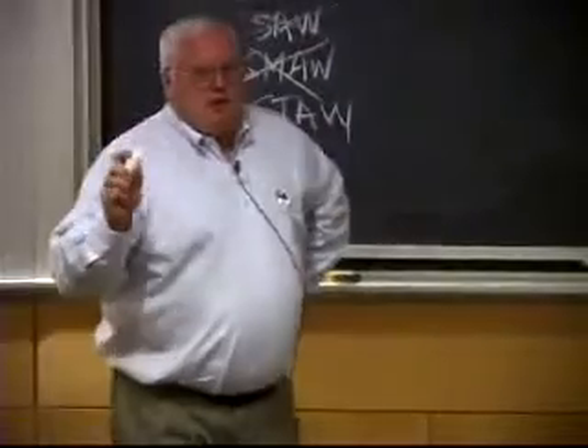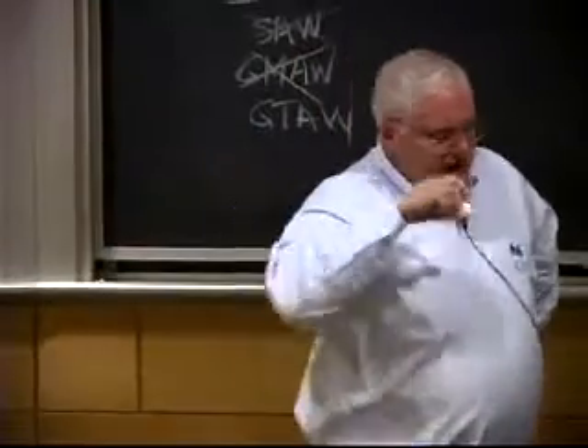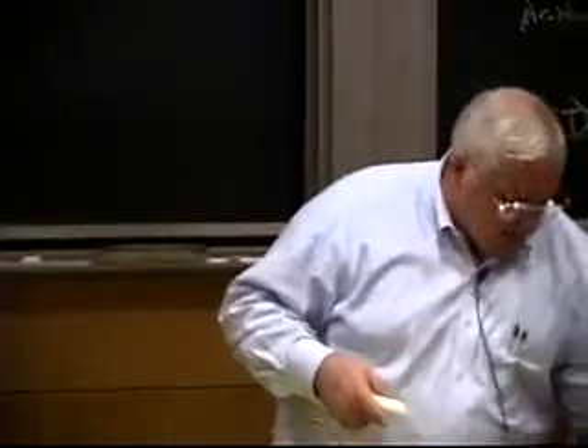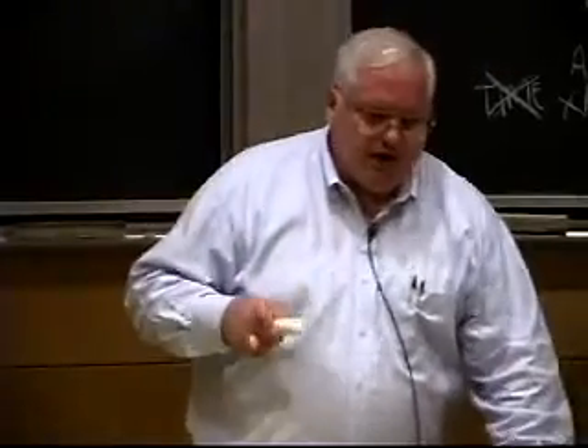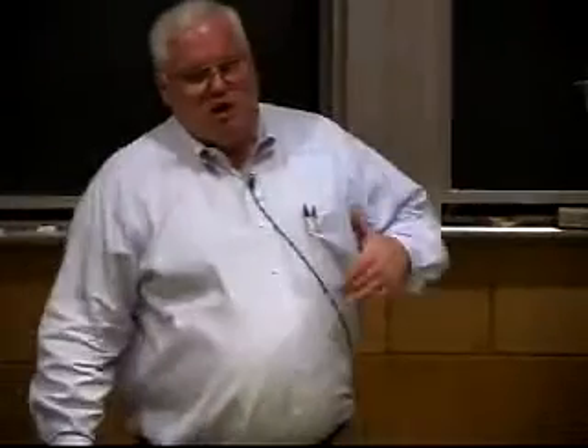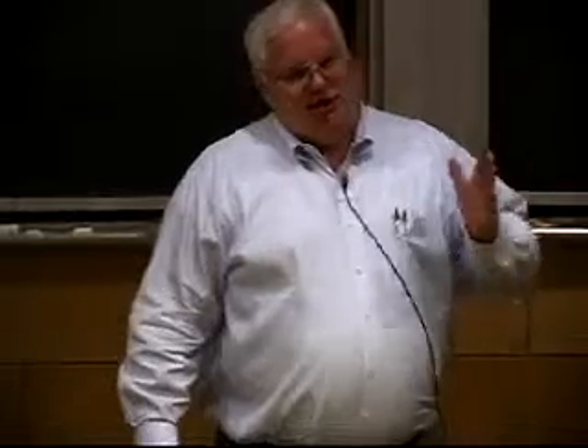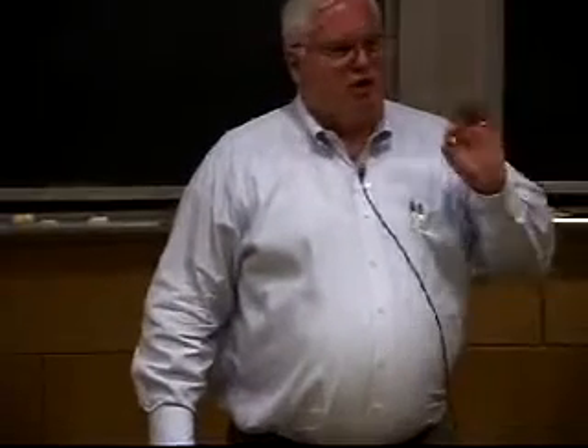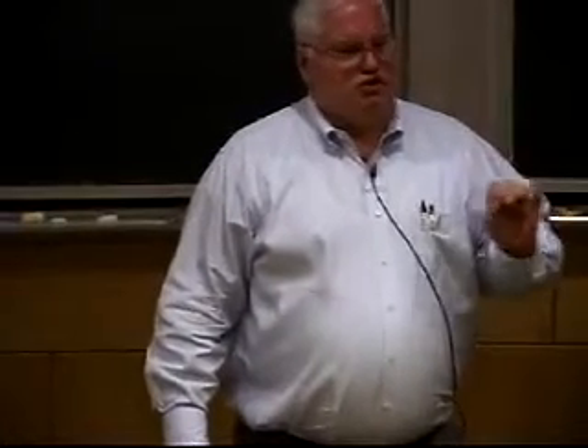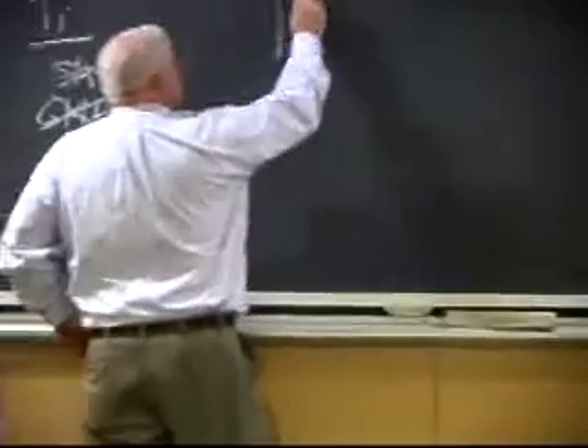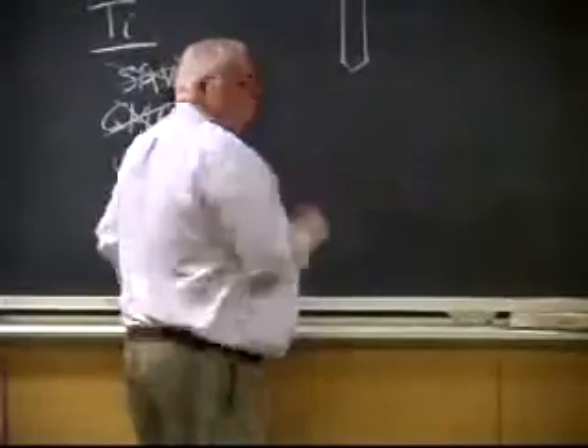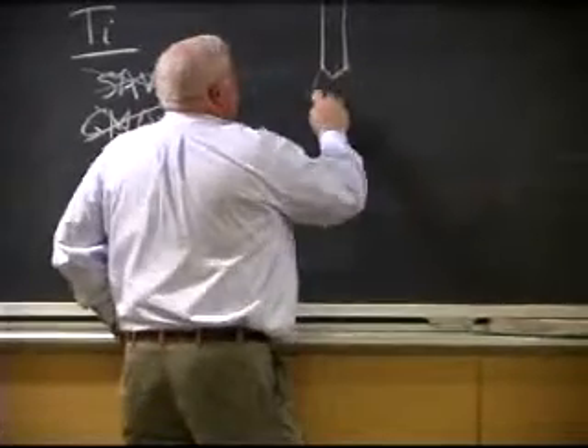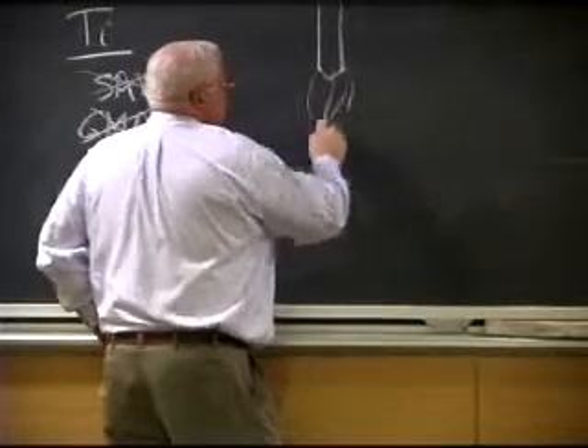If you look at the Soviets, they have 2 books, welding production and automatic welding, where they publish their work. In the 60s, Gurevich was publishing papers on what they called, it was translated as, semi-submerged arc welding. It wasn't semi-submerged arc welding at all. It was gas tungsten arc, where you use a great big tungsten electrode. This could be a 3/8 inch diameter tungsten electrode. You can have 1,000 amps on this thing.